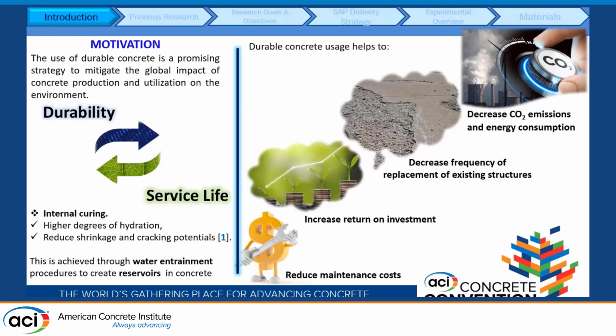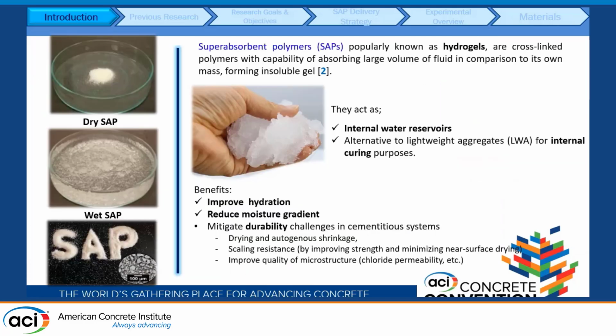And the best way to achieve this is through internal curing of concrete by water entrainment, where we create water reservoirs within the concrete matrix, which produces a continuous and continued water supply for optimum hydration. And one such way to do that is by the use of superabsorbent polymers, which are popularly known as hydrogels. They are cross-linked polymers with the capacity of absorbing a large volume of liquid in comparison to their own weight, thereby forming insoluble gels.